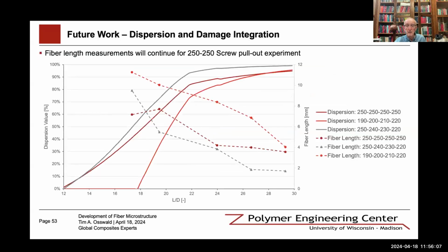model. And one of the things, this is where I want to end with future work, is what we did here. You see the dispersion in the solid lines and the fiber length in the dashed lines throughout the plasticating unit. And so this would probably be a beginning of where we know that the dispersion actually is completely coupled to the fiber damage model, because undispersed fibers, when they're still close together, protect each other. So low dispersion means low fiber damage, high dispersion means higher fiber damage. And so we have a coupled system that needs to be solved.